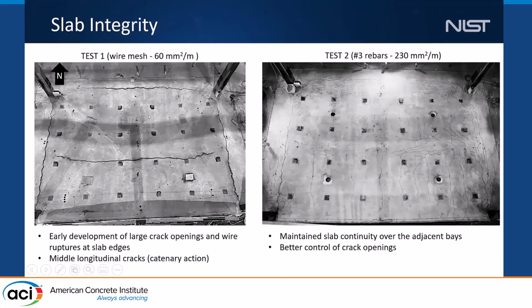This is a photograph of the top of the slab after the fire, after the specimen had sufficiently cooled down. As you can see, the test number 1 floor slab was reinforced with the wire mesh mat. As you can see, the large edge crack opening happened first, and that mostly happened during the early phase of the fire. It's not really captured in the test video, but other evidence indicates it. That allowed the large end rotation of the slab edges, which accelerated the vertical displacement at the middle, eventually developing the crack opening at the center of the test bay.